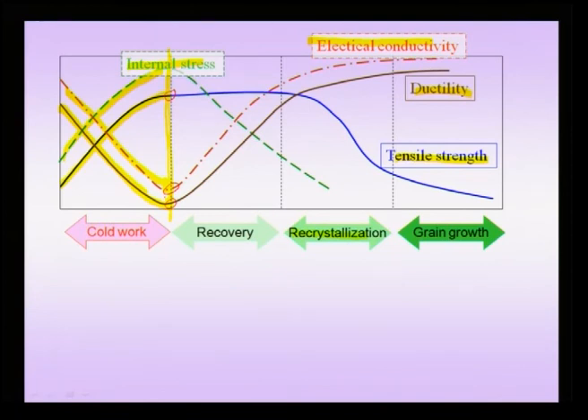Now if such a material is held at a temperature so that I just caused recovery, then what happens is that you can see that some of the properties are severely affected. Like for instance, now there is a serious increase in my electrical conductivity. The ductility tends to recover a little bit, my internal stress also falls down a little bit, but not totally, but my tensile strength is still not changed much because I have an overall high amount of dislocation density.